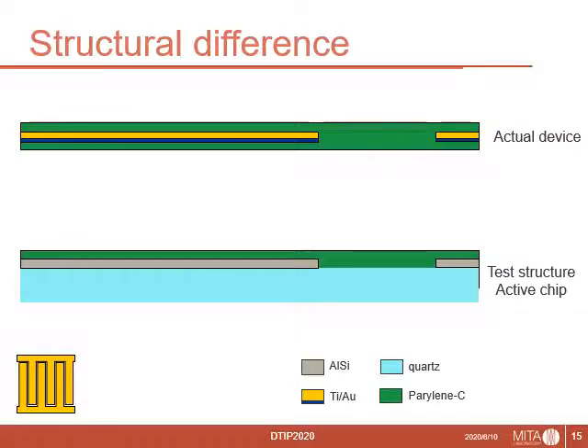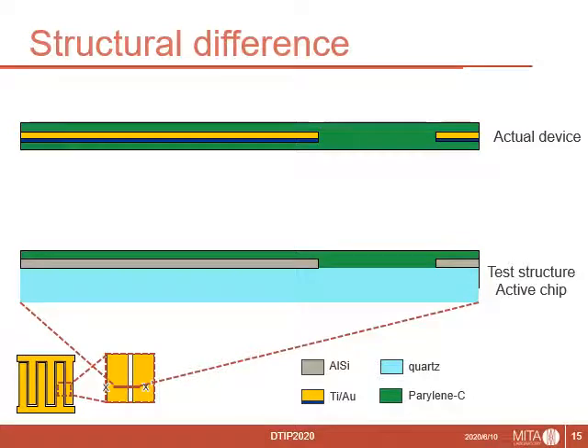These are the cross-sectional views of the actual device and the active chip of the test structure. There are 2 differences between them. Firstly, in the actual device, the electrodes are sandwiched by Parylene C, while in the test structure, Parylene C only covered the top side of the electrode. This configuration was necessary to prevent electrodes from being peeled off.